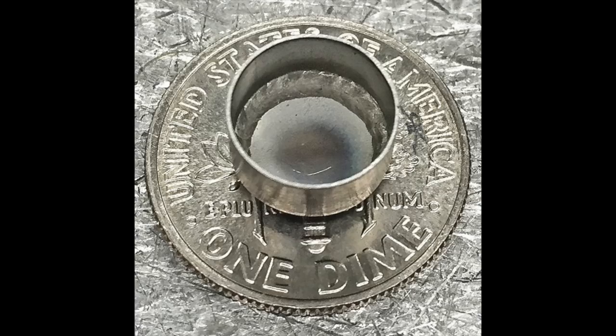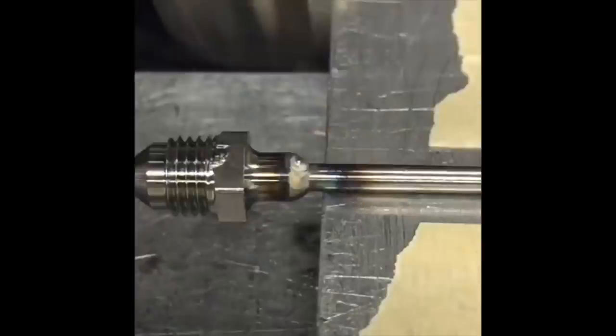So I've used helium mix specifically on titanium, and I haven't used it on any other metal except titanium. When I used the helium mix, I was purge welding the backside with a 10% helium argon mix, and the top side with a 15% helium argon mix. Opposed to straight argon, it helped bring the extra heat that I needed to make a full penetration weld, and keep it shielded properly.